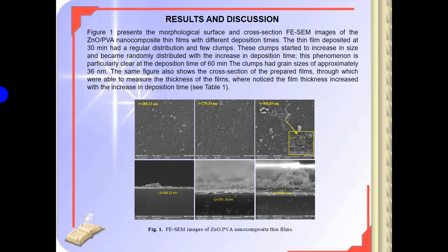Results and discussion. Figure 1 presents the morphological surface and the cross-section image of the ZnO-PVA nanocomposite thin film with different deposition times. The thin film deposited at 30 minutes had regular distribution and a few clumps. These clumps start to increase in size and become randomly distributed with increased deposition time. This phenomenon is particularly clear at the deposition time of 60 minutes. The clumps had a grain size of approximately 36 nanometers. The same figure also shows the cross-section of the prepared film, from which we were able to measure the thickness of the film, where the film thickness increased with increased deposition time, as seen in Table 1.